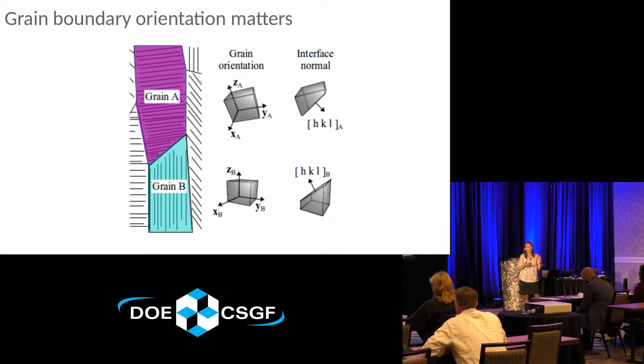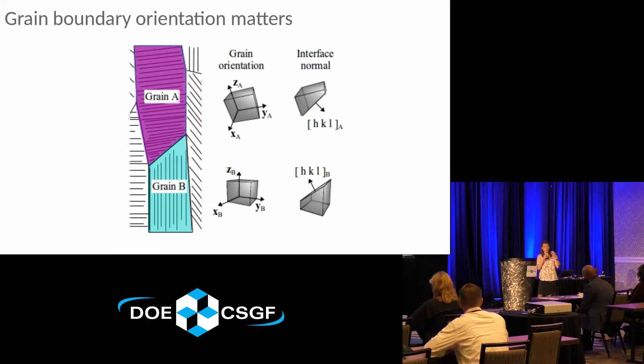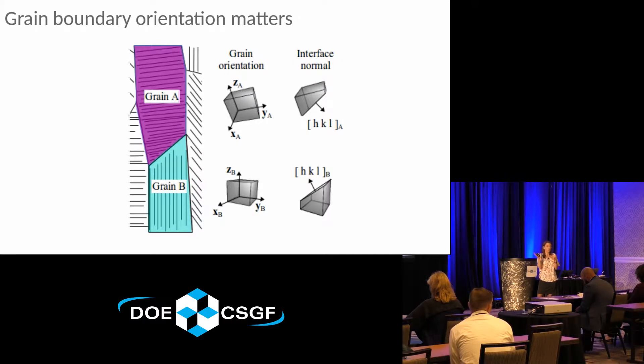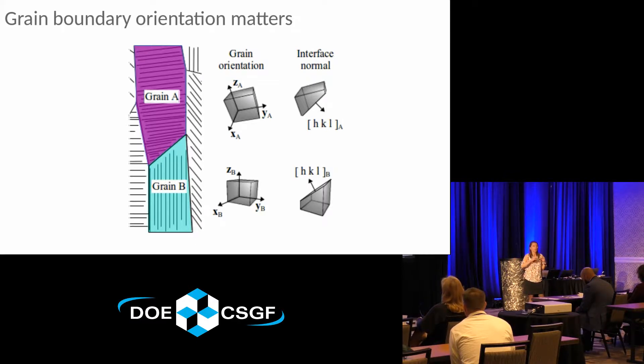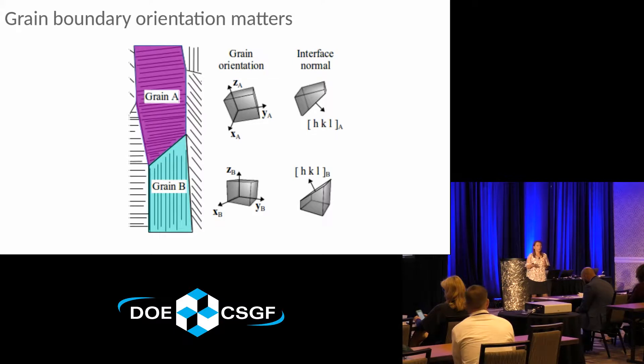This is not quite the entire story. Some grain boundaries may be the source of cracking failure; however, other grain boundaries with different orientations could in fact be resistant to failure — so resistant that a crack trying to propagate along an intergranular path is forced to go transverse through the bulk of the material. The orientation space associated with grain boundaries is a really vast geometric space with five different parameters that describe what a grain boundary orientation will look like. Naturally, we might want to engineer materials with more grain boundaries that have crack-resistant, corrosion-resistant properties and fewer susceptibility problems.